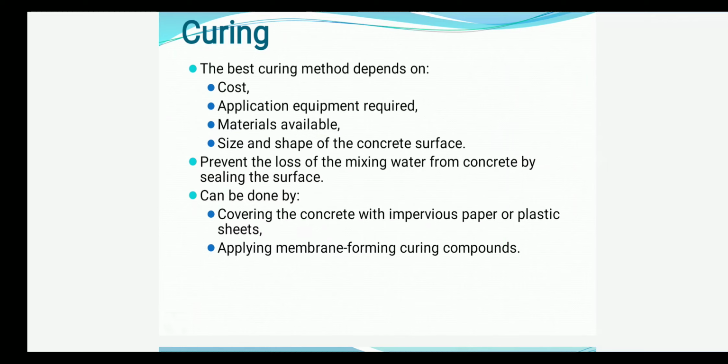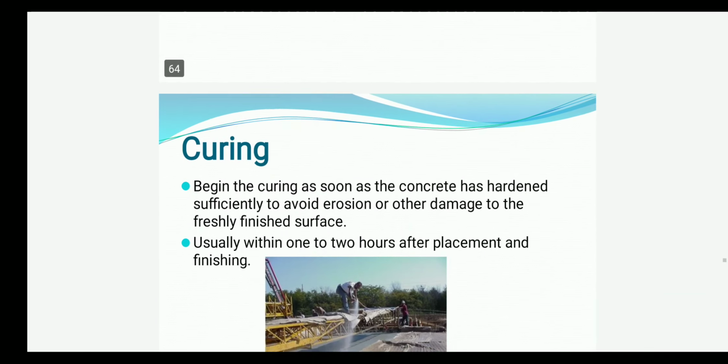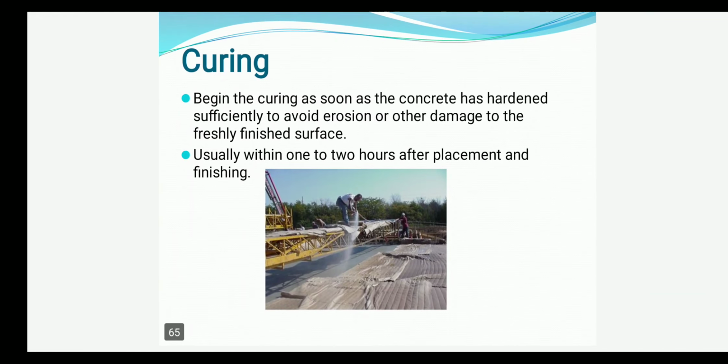It prevents the loss of mixing water from concrete by sealing the surface. There are a lot of processes or methods of curing that we are going to see in the next slides. Begin the curing as soon as the concrete gets hardened sufficiently to avoid erosion or other damage to the freshly finished surface. Usually within 1 to 2 hours after placement and finishing, the curing should be started.